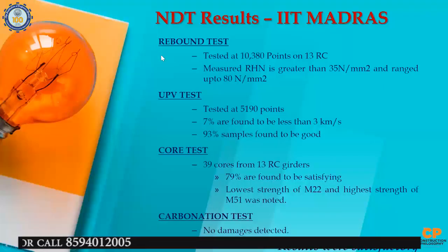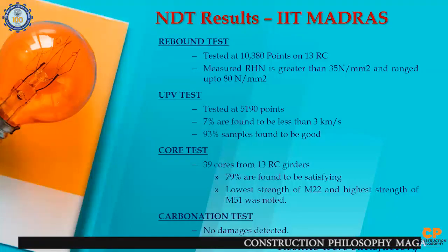And what were the results or findings from the NDT tests? From the rebound test, they tested at 10,380 points on 13 RC girders, and the measured rebound value is greater than 35 Newton per mm square and ranged up to 80 Newton per mm square. So 35 Newton per mm square was the strength for which the reinforced concrete was designed. And they did the UPV test at 5,190 points, and 7% were found to be less than 3 kilometre per second, and 93% of samples were found to be good, with values ranging from 4 to 4.5.